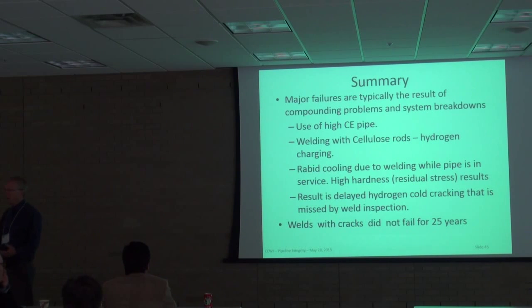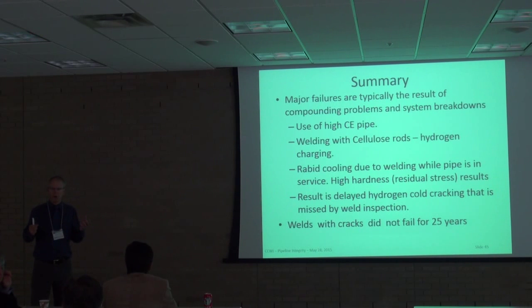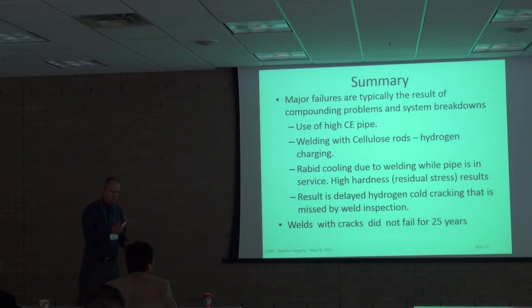And I've run into that a number of times. We were just doing a big risk assessment on a project today, for plants. And one of the things they wanted to know is that, well, these plants have been in operation for years, so we shouldn't have much of a concern about, say, low impact properties. No. I've seen several very catastrophic failures of pipe that was built out of A106 or non-impact tested materials, and it's still in the ambient environment where it can be minus 40. It just took sometimes 20 years, sometimes 30 years for the right set of circumstances to occur. When you get cold enough at the right time, the failure will occur. So these things can sneak up on you.